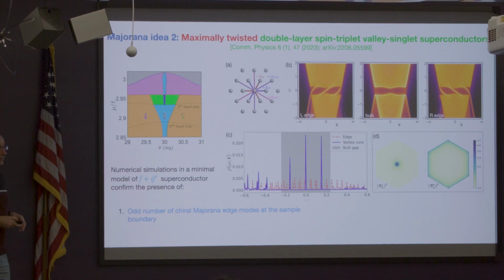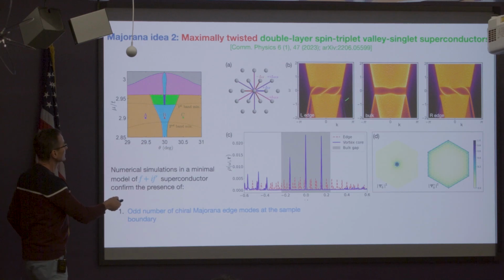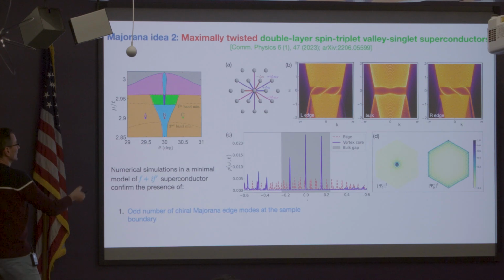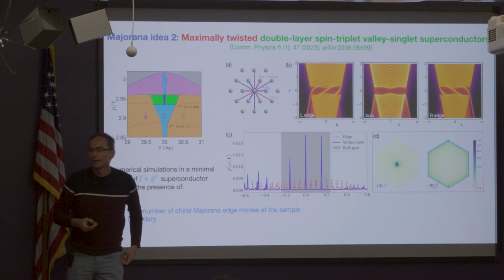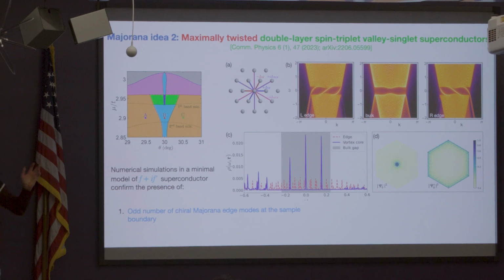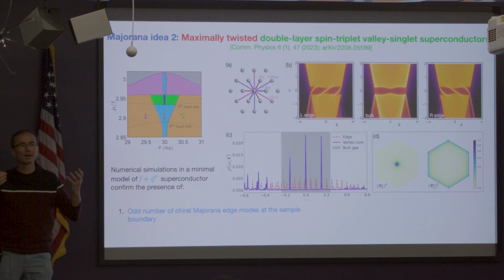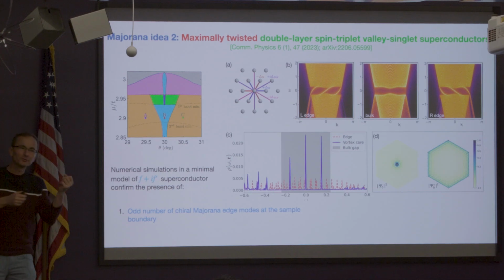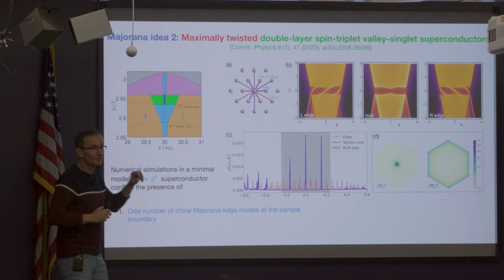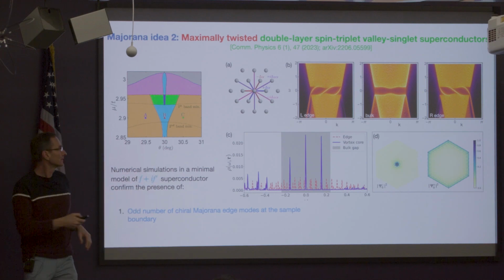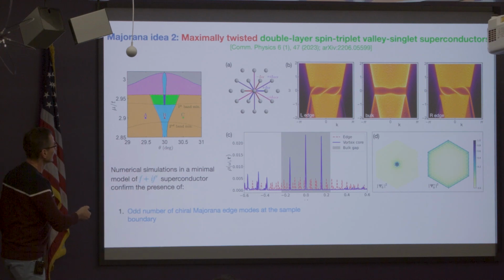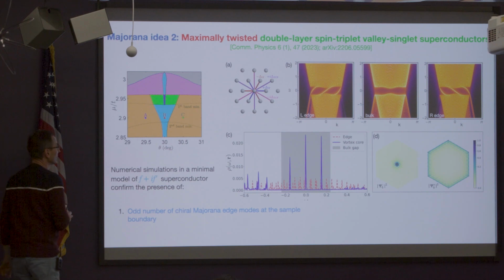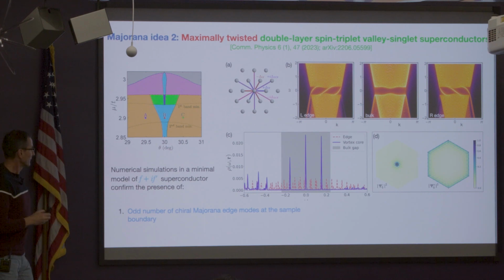But importantly, now you have an odd number. Okay? So instead of 4 as in d plus id, here you only have 3. And 3 is actually as good as 1. So what happens is when you have 3 Majorana modes, 2 of them can hybridize and go to finite energy, but one of them has to stay at 0. So this is exactly what's happening here. So an odd number of Majorana modes is good.